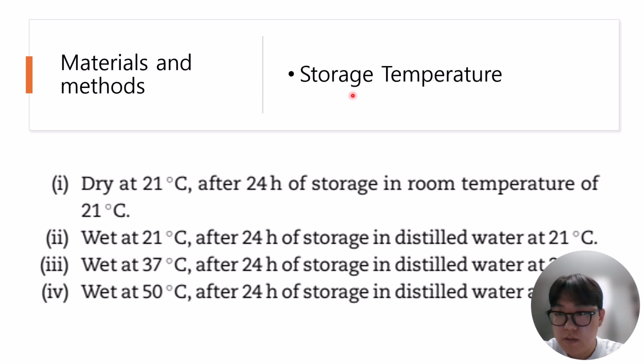Samples were tested under 4 conditions. First condition is dry at 21 degrees Celsius. Second, wet at 21 degrees Celsius. Third, wet at 37 degrees Celsius to simulate body temperature. And fourth condition, wet at 50 degrees Celsius to simulate brief exposure to hot food or drink. This helped simulate real oral environments.